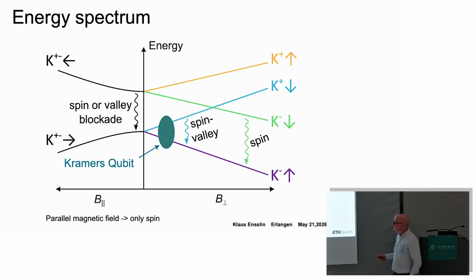The experiment that I've shown you before was done at higher magnetic fields. It was done here. And there you see the green state decays into the violet state, which is the same K, and you flip the spin. So the time scale that I've shown you was a pure spin flip, not a valley flip, right? Now you see you can flip the spin, you can flip the valley, or you can flip the spin and the valley. So it's much richer than the qubits in the other material systems.